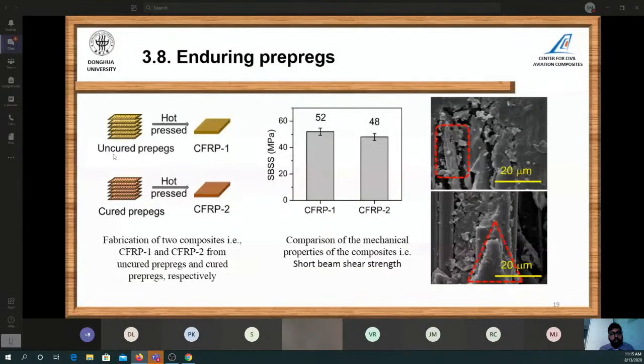Also, we worked on enduring prepregs, because for the carbon fiber reinforced composite industry, there are several issues with prepregs: the life of prepregs is not long enough. We need to store them in cold storage, which is an additional burden on the cost as well as on their processing. We cannot use them, and the waste in the prepreg industry is very high, so we can use this resin for making the composites.